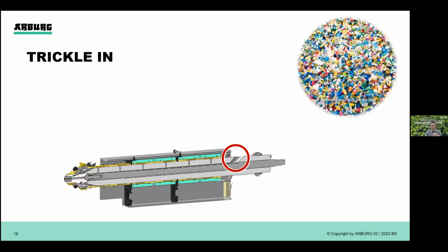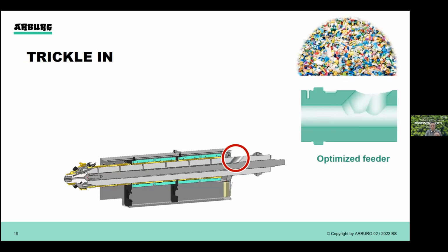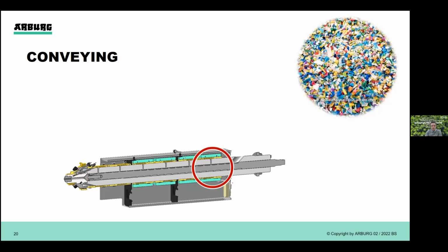Beginning with the hardware, let's look first at the trickle-in behavior. The filling or trickle-in geometry is mostly arranged at a 45-degree angle in most of our plastification. We come from the all-rounder idea, which should make it possible to use our cylinder modules extremely flexibly. But this is not the most flexible solution for preparing regrind, and therefore we have improved the filling geometry, as you can see on the green picture. An additional vertical hole in the intake area, at a 90-degree angle, is intended to improve the trickle-in behavior and the subsequent sliding of the regrind, to ensure that especially the grist material is fed properly into the injection unit.